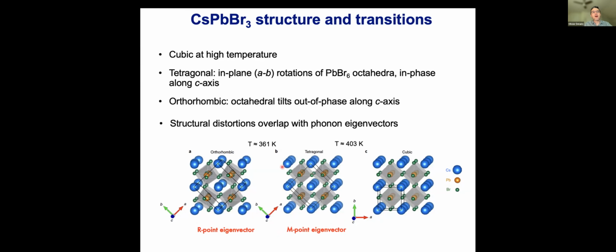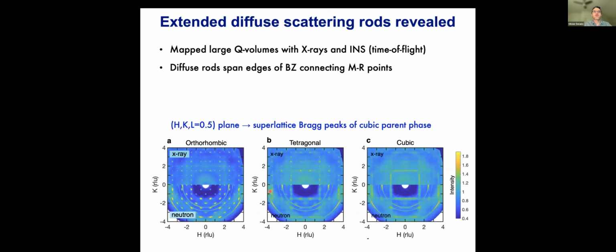So I'll start by showing you what I mean when I said there are strong fluctuations away from the average crystal structure. So this is revealed in diffuse scattering. And so one of the main points of my talk is that it's very useful to couple inelastic studies with diffuse scattering studies. And we see that directly here. So if you look at the cubic phase of the cesium lead bromide in a plane L equals a half, there are no Bragg peaks, but you still have a lot of scattering that's got pronounced structure in the form of these rods that actually follow the edges of the cubic Brillouin zone.